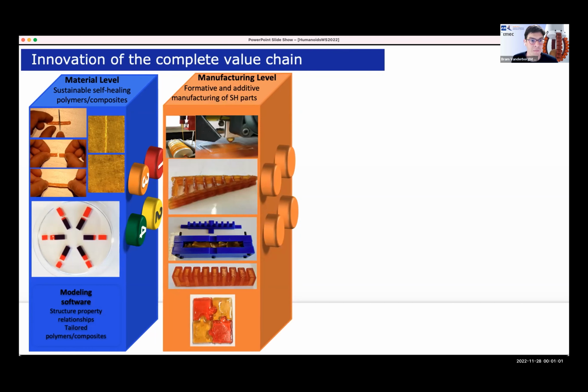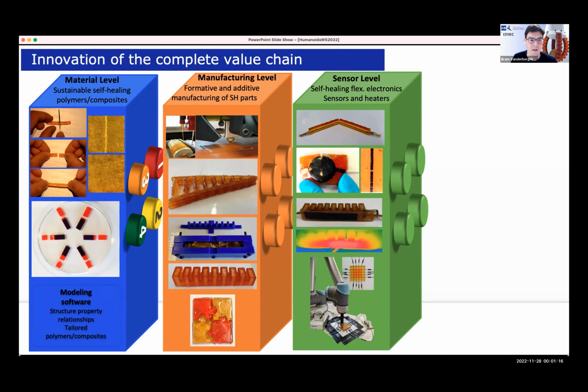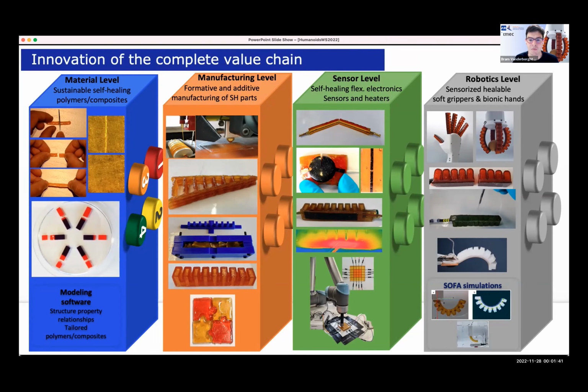Then we also study different manufacturing techniques. Often we use 3D printing, but if you want to go to larger quantities, you can also go to molding. And it's even possible to combine different manufacturing techniques. We not only made non-conductive materials, we also added fillers, magnetic or carbon black and so on to make it conductive. So we can use it as a sensing element, but also as a heater, on which I will come back later. Moreover, it's also the same self-healing material, so the sensing element itself can be damaged and healed. And then, of course, we can make different robotic components out of it.